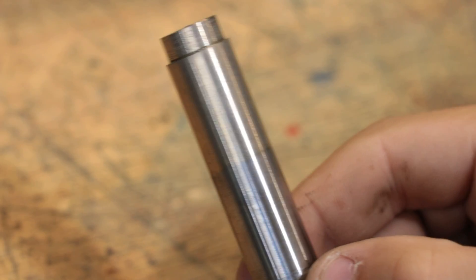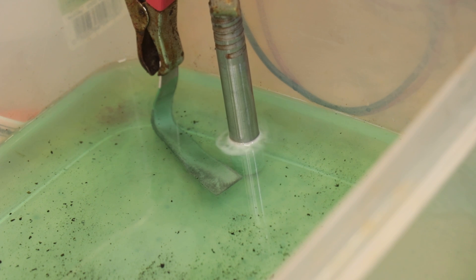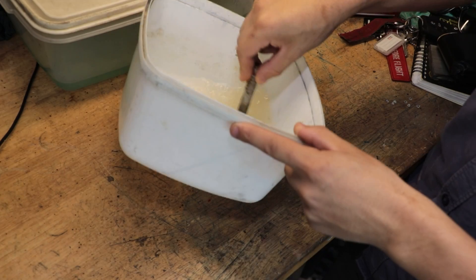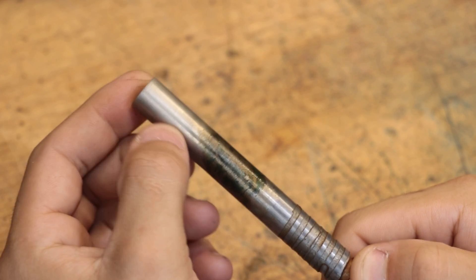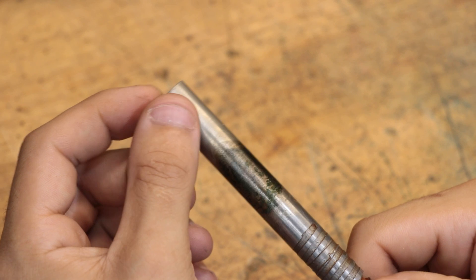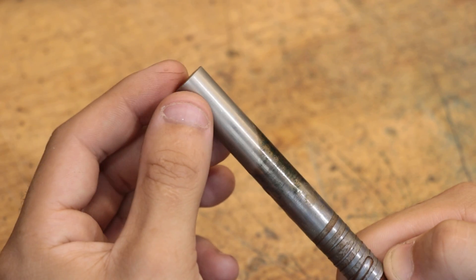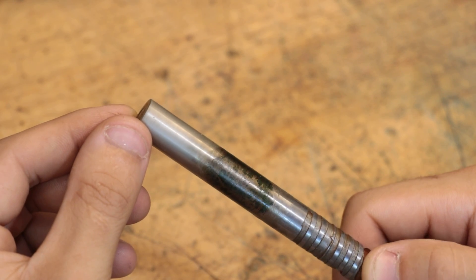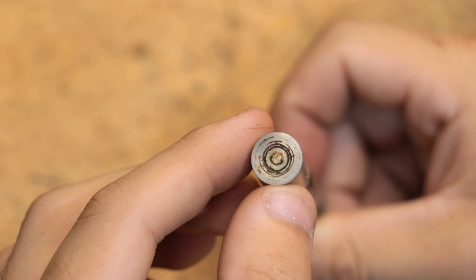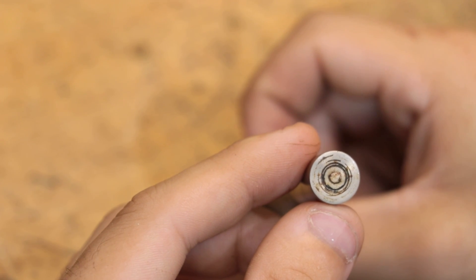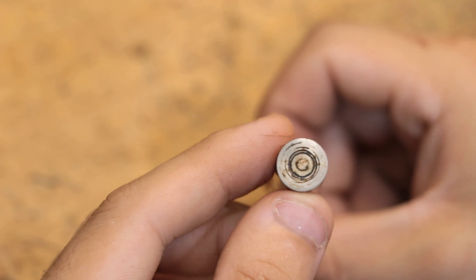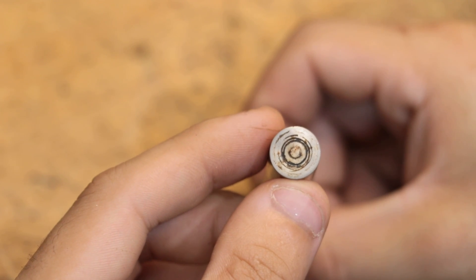So what I did was, I got a second test piece, and I gave it a very similar coating to the first. I then gave it a good coating of salt water, and then left it overnight to dry. And this is the result. You can clearly see the points at which the nickel stops and the rust starts. And that goes to show that even a very thin coating of nickel plating is very corrosion resistant. I'd say this is a really great result. It's also worth noting though, that I wasn't able to sand down some of the grooves at the bottom of the part, and there must have been some oxide or contamination inside the grooves, because they obviously didn't receive any nickel plating, and they have corroded.